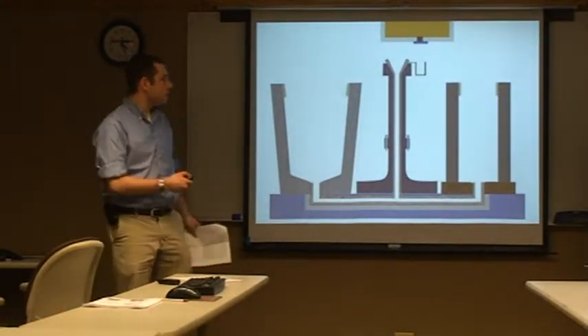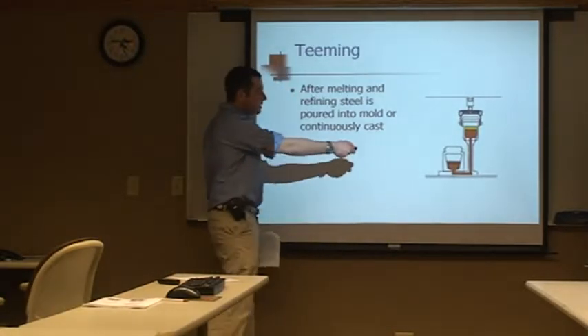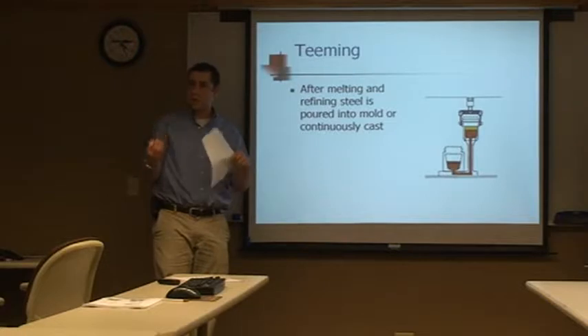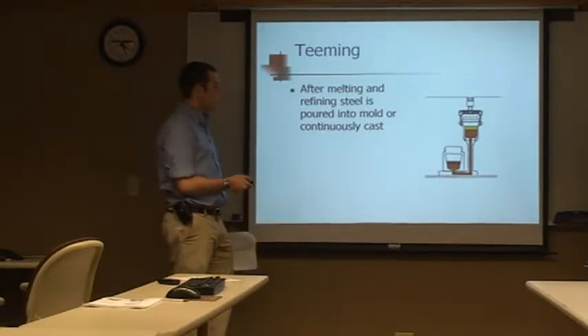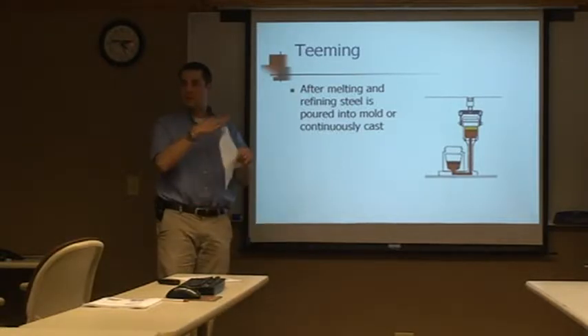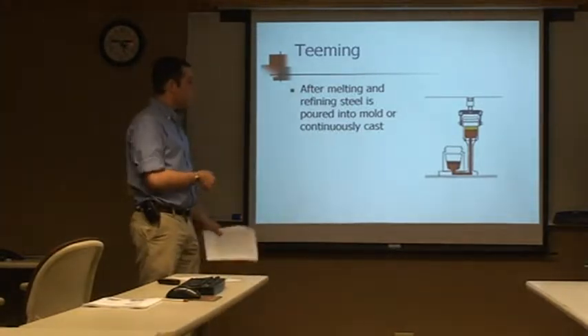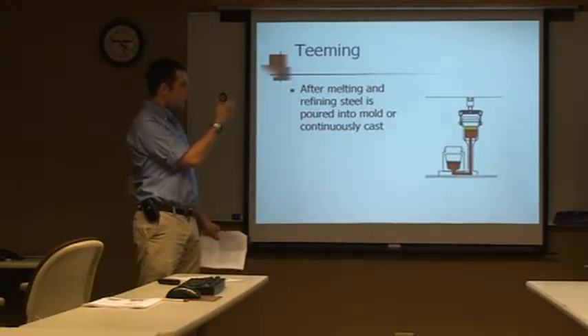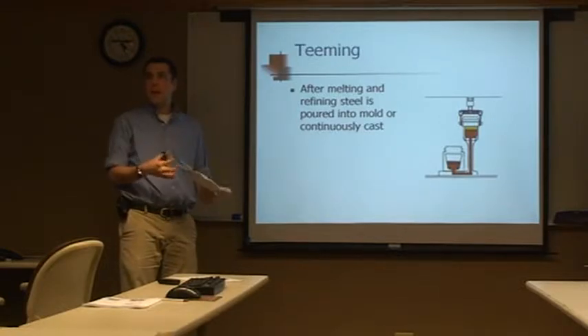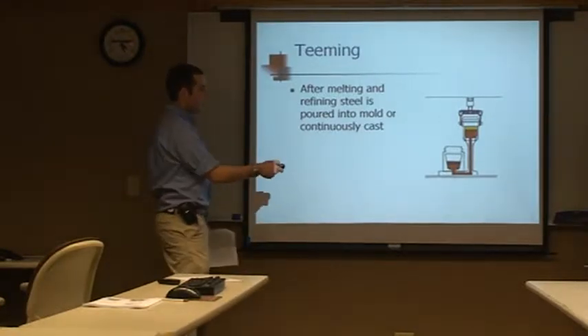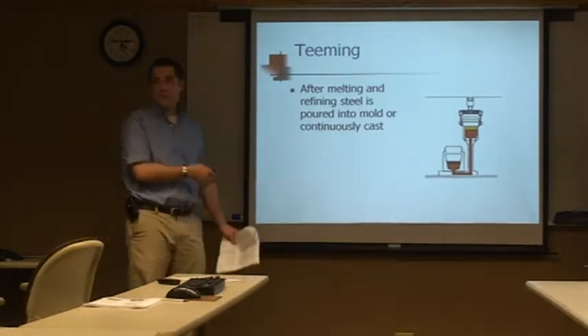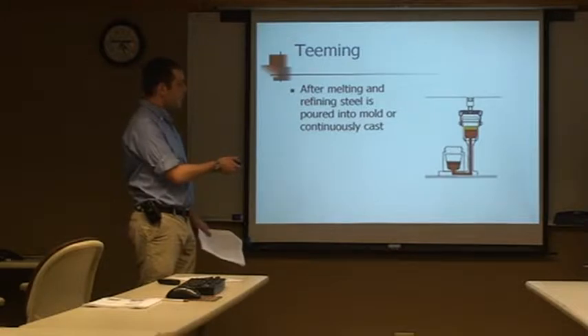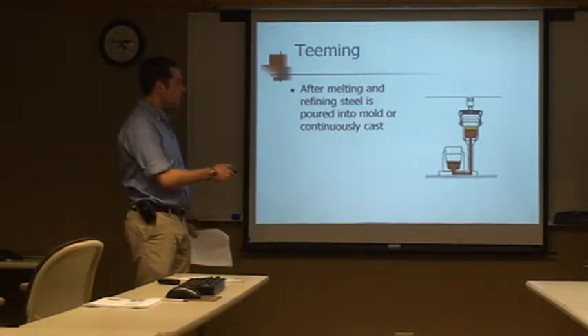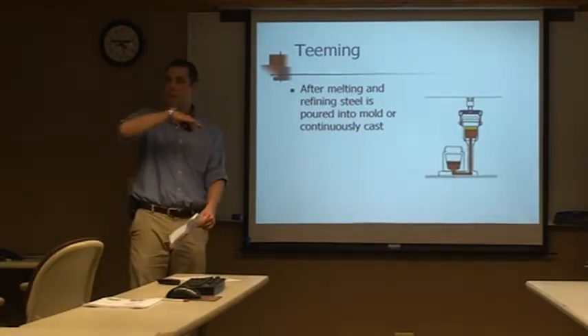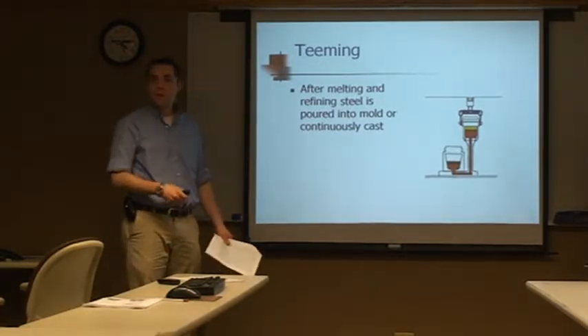Is that also to keep the slag at the top of the... Well, the ladle is teemed, this is the ladle here. It's teemed from the bottom, similar to the way the arc furnace is, only it's not tilted, we just open a hole in the bottom. So we drain all the liquid metal and just leave the slag in the ladle. Occasionally some slag comes out at the bottom of the ladle, and in that case we'll shut everything off and keep that slag in the trumpet, because we don't want that getting into the ingot mold. But ideally we just get pure liquid metal and we leave the slag in the ladle, and we dump that out afterwards by tipping the ladle over before we reuse the ladle in another campaign.